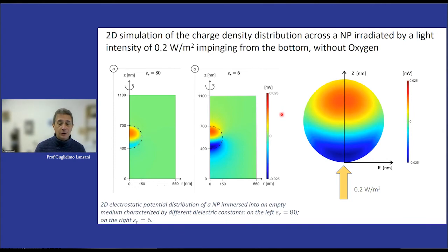It's still a 2D simulation in which we put the nanoparticle in an environment with a dielectric function of 80 or a dielectric function of 6. Well, of course, it's very easy to understand that when the dielectric function is 6, the potential and the field, this is potential, extend much more than when the dielectric function is 80. So it means a screening environment such as water would confine the electrostatic coupling, but if there is a dielectric, the electrostatic coupling expands over a much larger range.